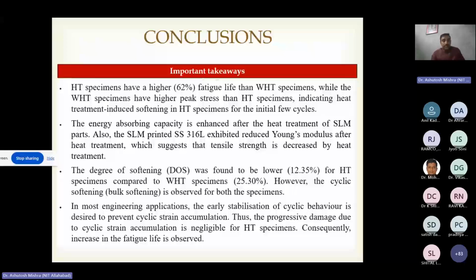The second takeaway is that the energy absorbing capacity is enhanced after the heat treatment of the SLM part. Also, the SLM printed SS316L exhibited reduced Young's modulus after heat treatment, which suggests that tensile strength is decreased by heat treatment. This is particularly for this study. However, this requires further consolidation because the reason for microstructural coarsening or microstructural refinement is still not very clear.